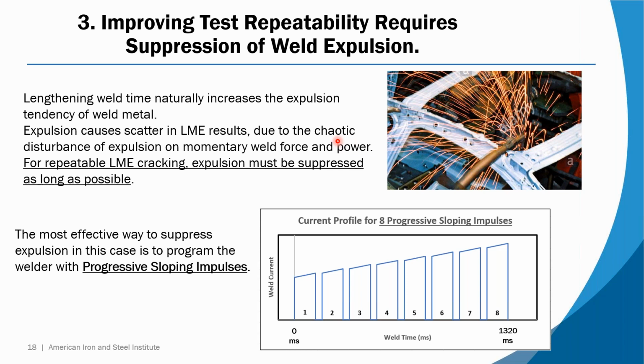It could happen anywhere during the weld schedule, but at that particular moment when it happens, you have molten metal leaking out. Current starts going through the molten pool that's frozen quickly, and current density changes. The resistance of the weld changes because now you have a shunt path, and force changes because you just shot out a bunch of metal. The electrode has to advance, and until it does, you have this momentary flutter in all your main input parameters.